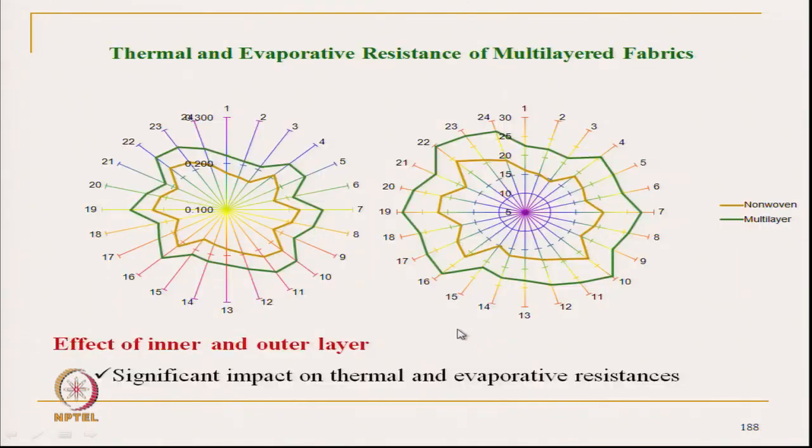So, here again a similar trend is observed for thermal resistance and evaporative resistance. In thermal resistance, the inner and outer layers have less effect than on the evaporative resistance. The significant impact on thermal and evaporative resistance is there for non-woven fabric, but the effect is more in the case of the evaporative resistance.